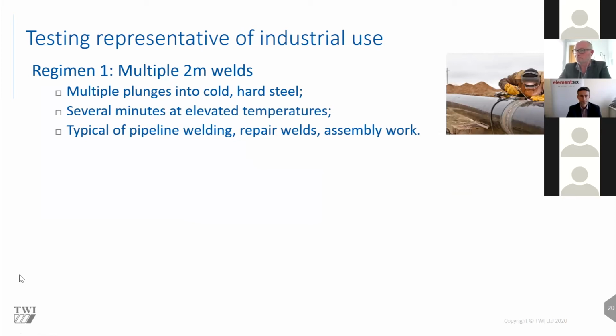One is where we've been doing multiple short welds, typically about 2 meters long. And this is perhaps typical of repair welding and pipeline welding, where the welds themselves are short and the tool is only at elevated temperature, typically around 1,000 degrees for several minutes. And the wear life of the tool is probably dominated by the plunge into the cold, hard steel. And that happens multiple times per tool.